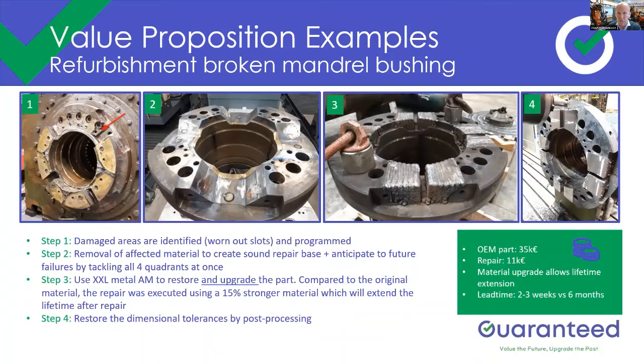Now, this case is also a very nice example to illustrate what we can do in terms of refurbishment, in terms of upgrading, because if you compare the original material that was used to produce this part to the new material which we deposited, the new material has a tensile strength which is about 15% higher than the original part, which actually means that the lifetime after repair will be longer than the original part. So again, besides the pure cost savings that resulted from repairing this part instead of buying a new one, there will also be secondary savings that can be realized later on, which are related to the increased lifetime of the component.